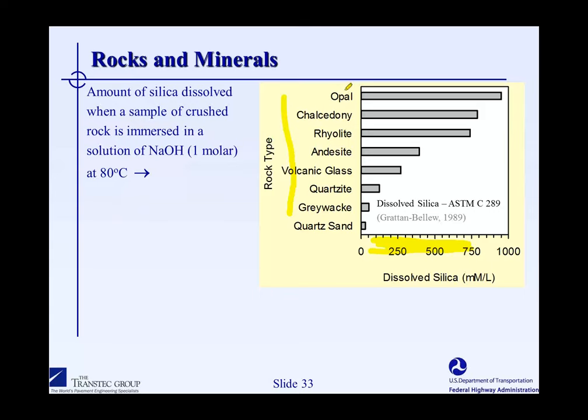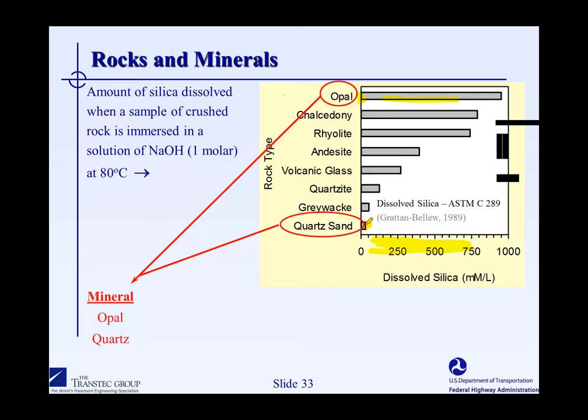And you can see that some minerals, like opal up here, are very soluble. They're highly reactive and a lot of the silica will pass into solution as shown here. Whereas a mineral like quartz, well crystalline quartz, shows almost no solubility at all and very little silica passes into solution. Let's concentrate on those two end members because it's interesting to look at them further.